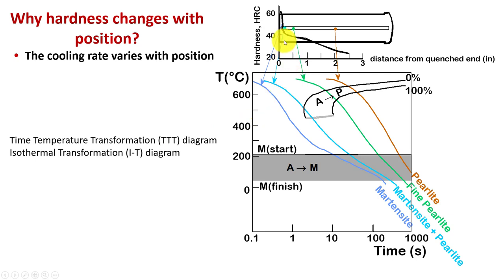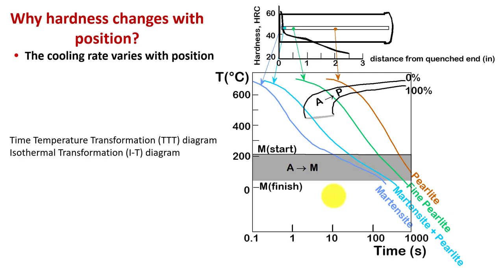The way we establish these diagrams is to take some alloys, a bar of material, do this Jominy test, and look at each interval of measurements and look at the predominant structures under a microscope. They create this graph representing that steel — every steel is going to have a different graph. We're going to look at the ASM Heat Treaters Guide to find these for each steel.